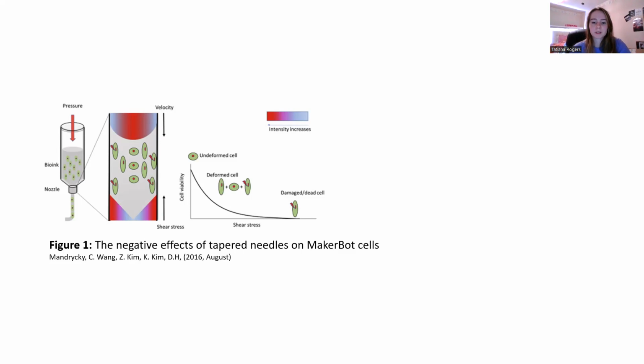Extrusion-based printers at MakerBot currently use GelMA, and GelMA has a high viscosity rate. Gelame often fails to give an environment suitable for extracellular matrix to form, and using gel-based inks will fail to produce a proper 3D scaffold. And GelMA is a fast degrading material. Once put mechanically into the body, the 3D scaffold will fall apart over time.